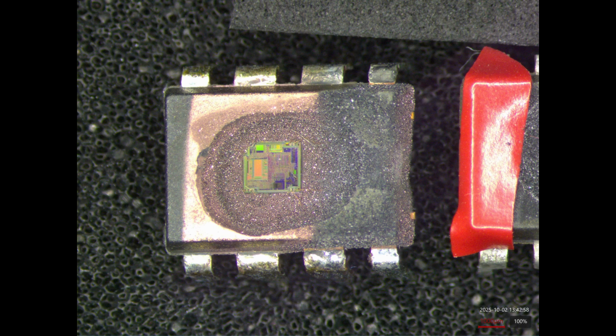And just to show how far things have come, this is another decap of the same chip that I did early on when I was starting out. This is in the 8-pin DIP package. You can see it's got a little bit of gold residue on it from SEM imaging years ago. But the important bit I want to call out here is the right side of the package is completely obliterated by acid spilling out over the edge and bubbling up, and also the diameter of the cavity, which is more rounded than rectangular, is just enormous, and there's so much destruction around the die. If this had been a small QFN or something, it would be gone.